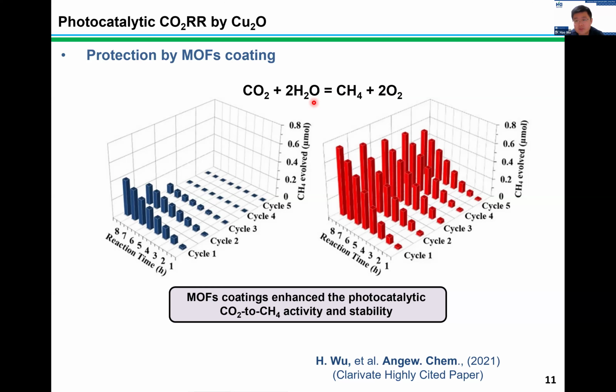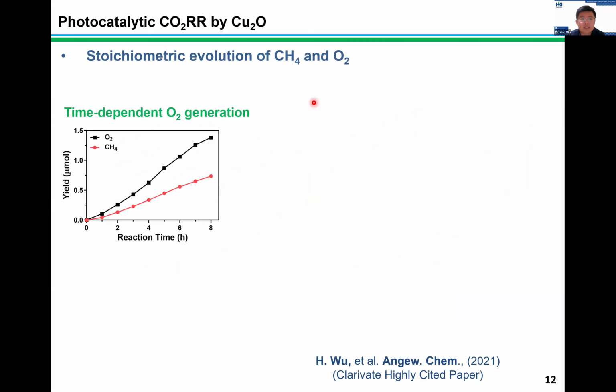And meanwhile, in photocatalytic carbon dioxide reduction, the stoichiometric evolution of products is always a focus of the community. As shown on the slide, the produced methane and oxygen should be in a 1:2 ratio. To prove that, we did time-dependent experiments, and our results indeed show that the produced oxygen and methane are in a 2:1 ratio. This is a very important indication, and it suggests that the photo-induced electrons and holes are fully participating in such a reaction.